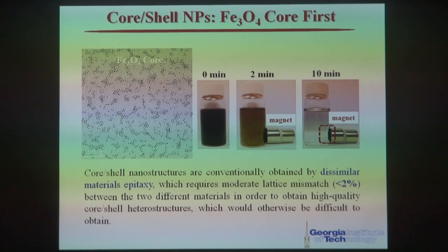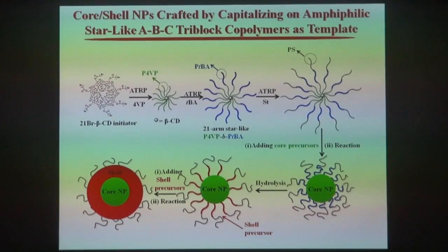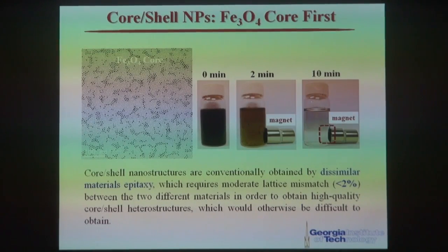Otherwise, you won't be able to get high quality coaxial nanostructures. However, by using this templating approach, as I discussed in this slide, we can circumvent the epitaxial growth limitation. So here, let me show you one example. We are making a magnetic iron oxide core capped by a ferroelectric titanate shell, a coaxial nanoparticle.